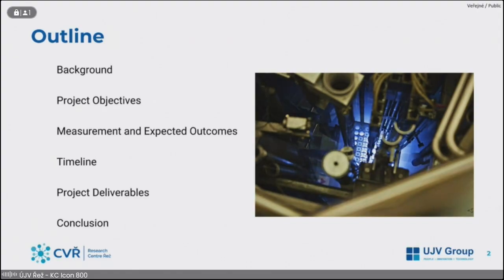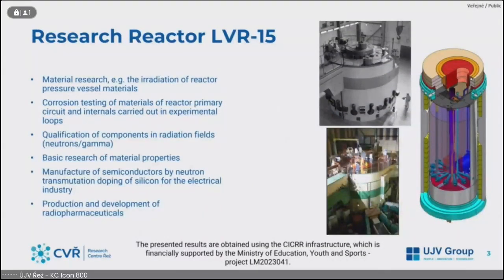Here on this slide, you see the core of the LVR-15 reactor in the shutdown state, and the nice Cherenkov radiation surrounding the fuel installed in the core. Calorimetric measurements in terms of reactor physics are aimed at the determination of the nuclear or radiation heating that occurs in the active core during reactor operation. Knowing this value is very important for the material irradiation experiments that occur at the LVR-15 research reactor.